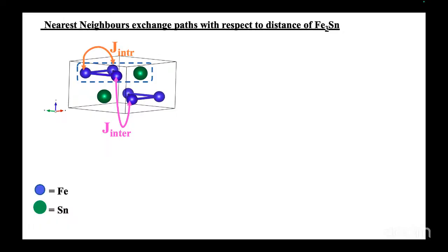So this is the unit cell that I used for the Fe3Sn system. I have calculated both the in-plane and the out-of-plane Jij interactions. Since the distance between the layers is quite comparable to the in-plane distance, we expect a large contribution coming from the interplanar interactions, and there should be a strong interlayer coupling. So we have evaluated both the in-plane and the out-of-plane with respect to the distance.